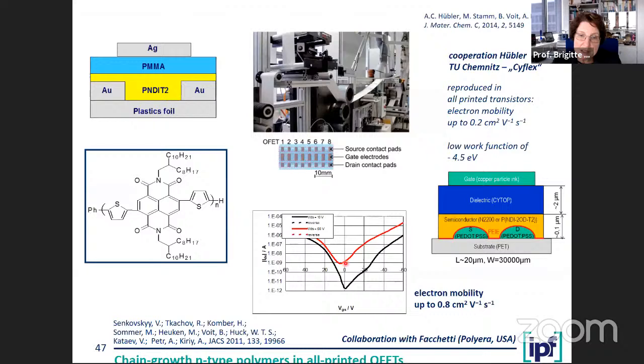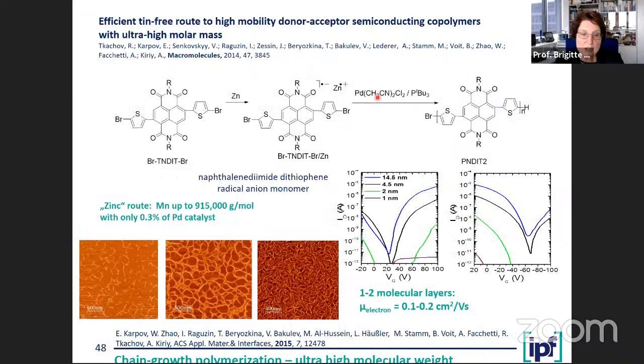The model devices under clean room conditions and under argon show a better mobility, but you have to understand that this mobility in our OFET material has been achieved in a process which is in ambient conditions. So there is air around, for example, and that needs a high stability of the material also under those conditions.